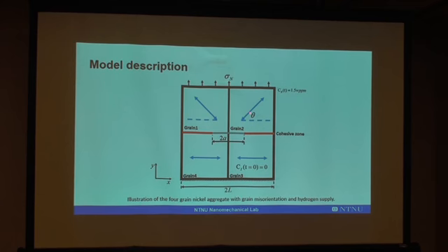We model the grain interior as orthotropic elasticity, and further assume that the local directions of the elastic tensor correspond to the crystallographic orientations of individual grains. For example, the local x direction corresponds to the 100 orientation. Then, if we rotate the elastic tensor, we are equivalently rotating the individual grains in space.